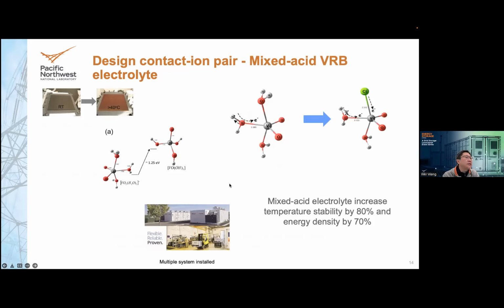So the first one is designing the contact ion pair. This is a commonly used method in the solvation study. For the vanadium redox flow battery, it has an issue with vanadium 5. The vanadium 5 electrolyte precipitates at a higher temperature. The figure showing here is the stack image after cycling many cycles at room temperature. We took it out, we took it apart, and then after cycling at a temperature higher than 40 degrees C, you can see the brown reddish particles that deposited on the graphite felt. Those are the V2O5 solid.